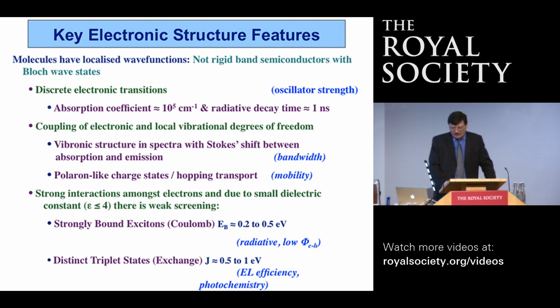We also have this coupling of electronic and local vibrational degrees of freedom. Again, thinking of my rubber sheet, if I drop my marble onto it, it will oscillate a little bit. That oscillation you can think of as a coupling between that electronic state and local vibrational modes of the material. It means that the excited state is actually coupled to vibrational states, and those vibrational states will then appear spectroscopically, so we'll see some features of those vibrational states. We'll see a series of lines that we call vibronic structure. It also means that if we want to move our electron around, we can't move it around as we would the marble on a nice piece of granite, where we can just zip it about. It can't move freely around.